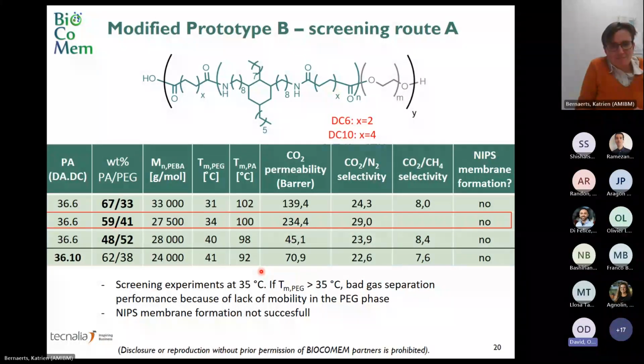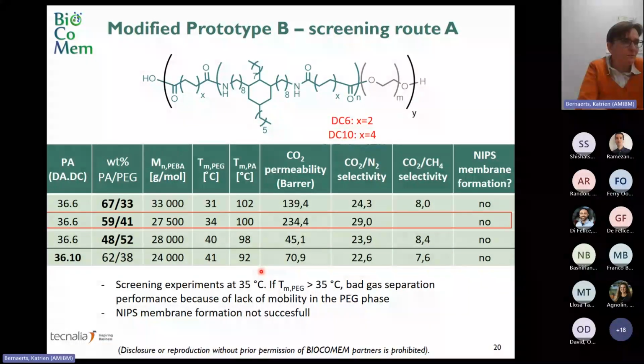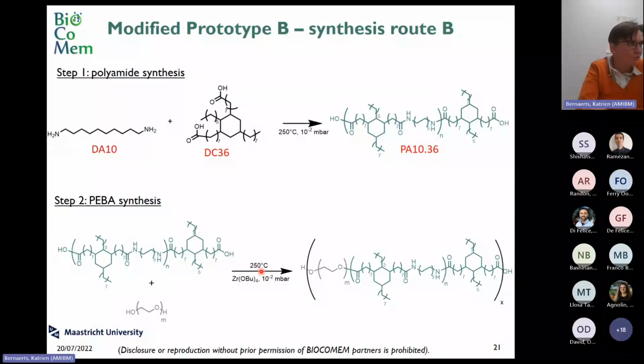And anyway, in all these polymers, we were able to make very nice thin films, dense films, to test the intrinsic gas permeation properties. But then we didn't manage to make a porous structure in water, because they were interacting too much with water, so these were swelling. So we decided that they cannot be used for NIPS membrane formation. So, as mentioned, we have problems with the membrane formation, but we also observed sublimation during the synthesis. That's why we decided to slightly change the synthesis route.